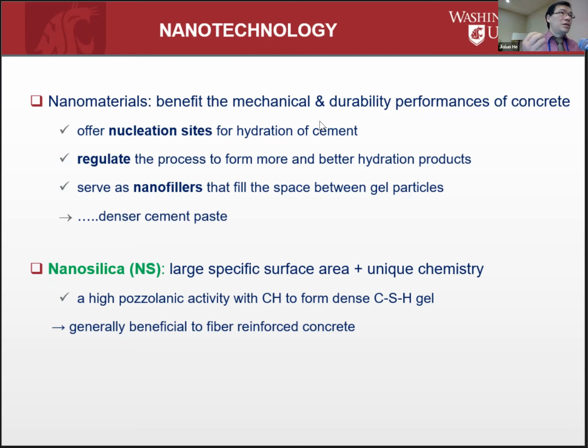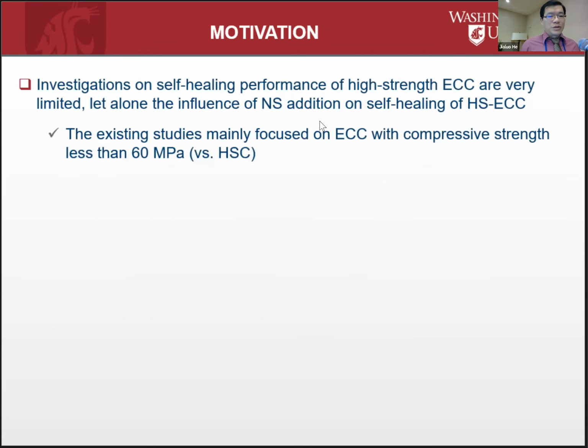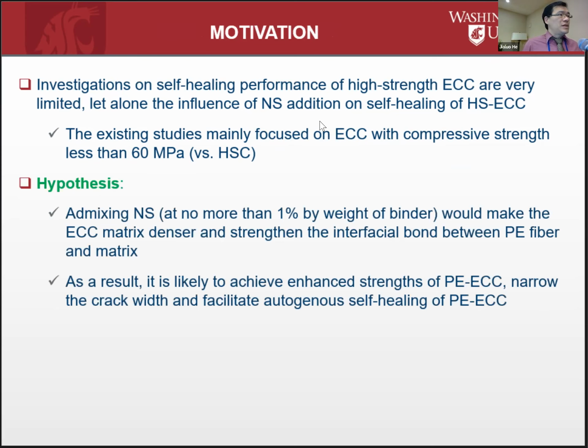The use of nanosilica has been explored in fiber reinforced concrete, including ECC. Then why the need for this work? The studies out there typically did not look at the high strength ECC or the PE ECC. So our hypothesis is that by admixing nanosilica at no more than 1% by weight of the cementitious binder, we should be able to make the ECC matrix denser, while at the same time improving the bond between the PE fiber and the matrix. Like I mentioned earlier, PE fiber is hydrophobic. They don't bond well with the matrix.